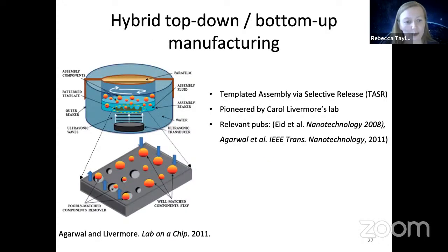All right. And so here is where I introduce you to templated assembly via selective release, and also where I glow about what is possible with the Nanoscribe and two-photon polymerization. Okay, so fundamentally, here's a method that was developed by the Livermore lab, which utilizes some sort of template with hemispherical pockets. And then you shake it, right? And if you have microparticles, microbeads, that have surface energy matched approximately to the material that you have that's pocketed, then you can actually have beads come and settle in those pockets. And if they're a bad mix, if they're a bad match, the kinetic energy just forces them right back out because you're shaking, right? But if they're a good fit, then those surface forces hold it in place. So the particles that fit well can stay in place.